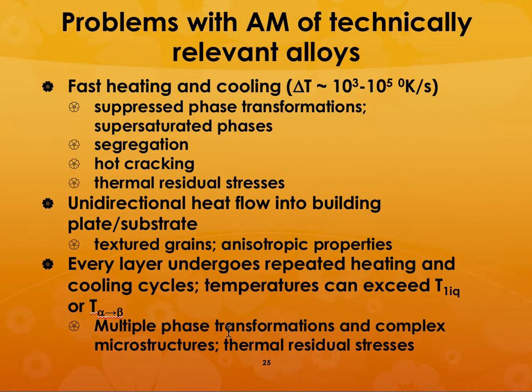And in some cases, you may have hot cracking. Then, because you are heating and cooling, you may have thermal residual stresses. One thing to note is that you are directing heat flow in one direction only, into the building plate or substrate. So that means you can have textured grains, and you will most definitely have anisotropic properties.